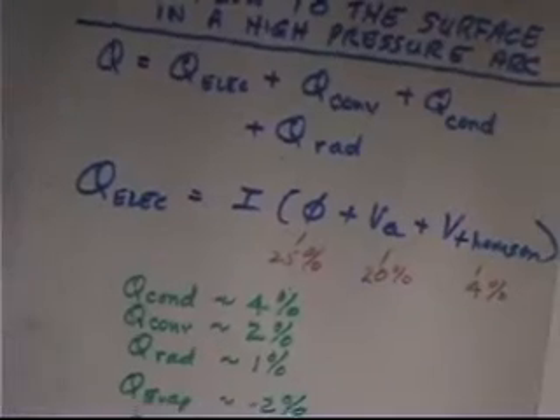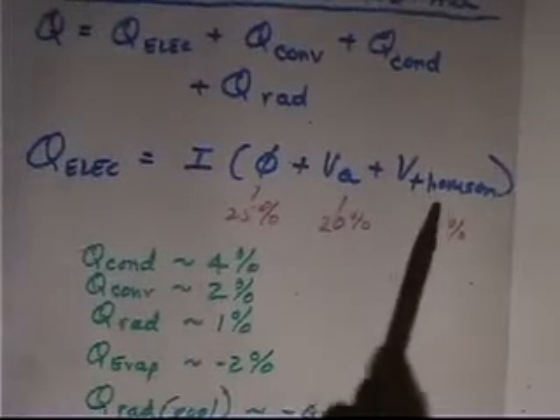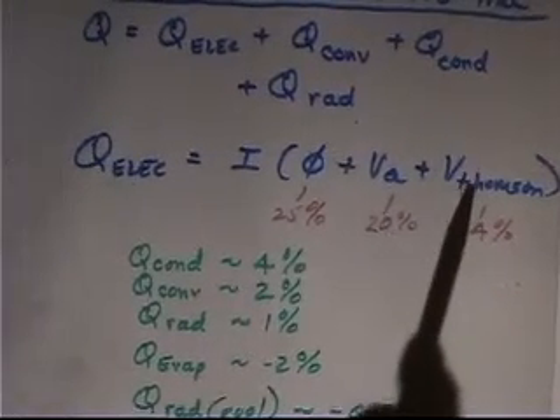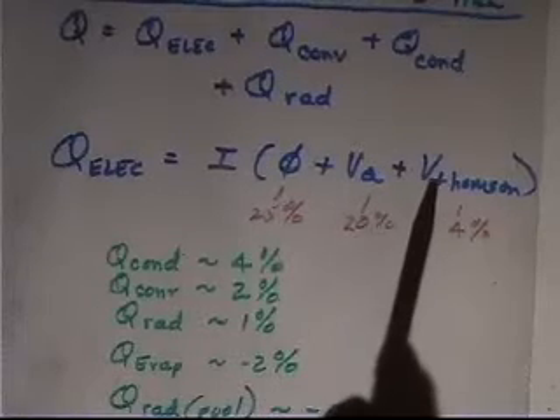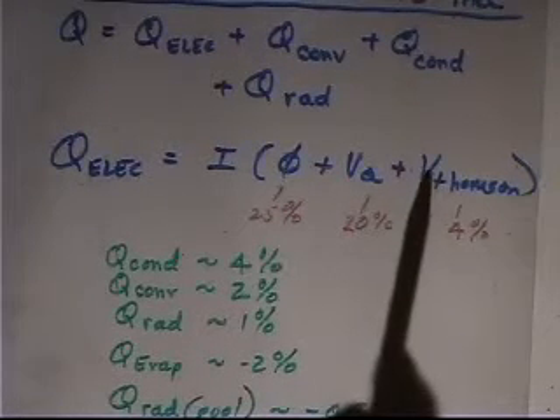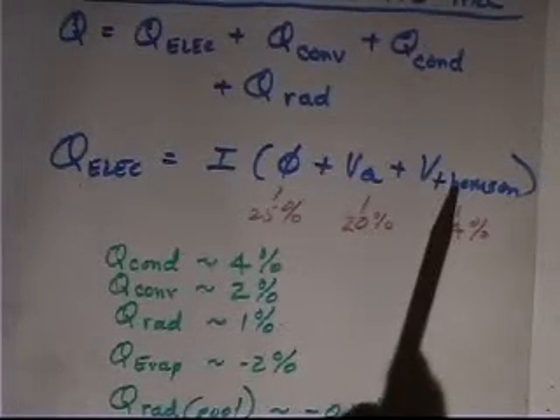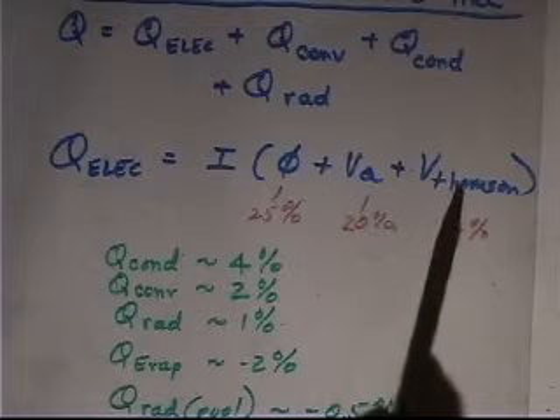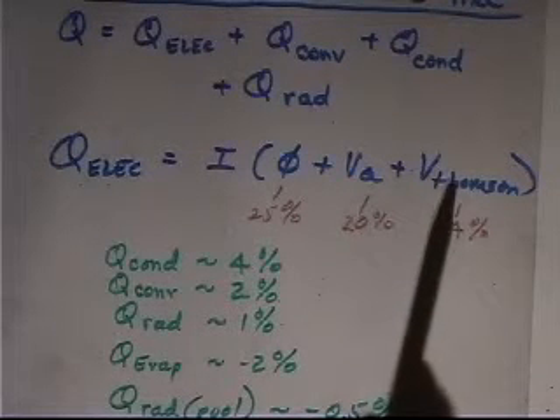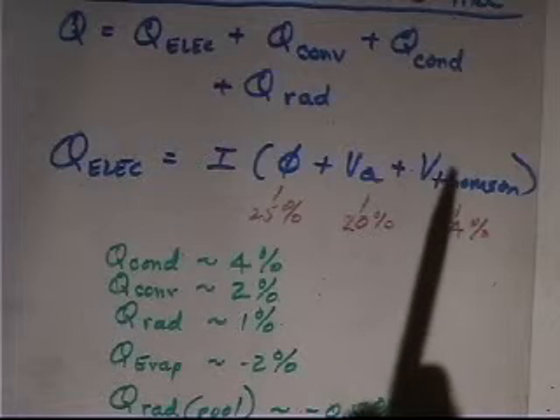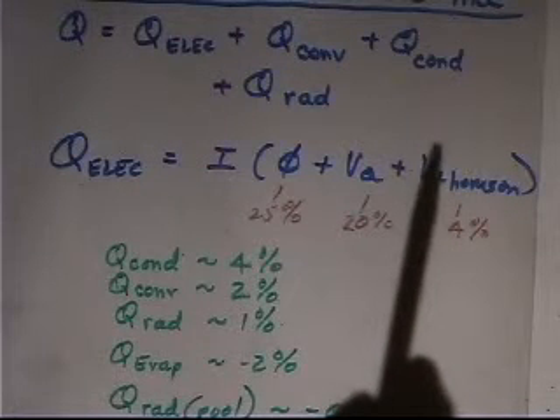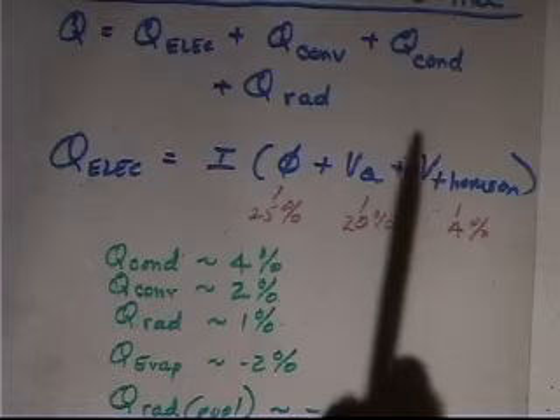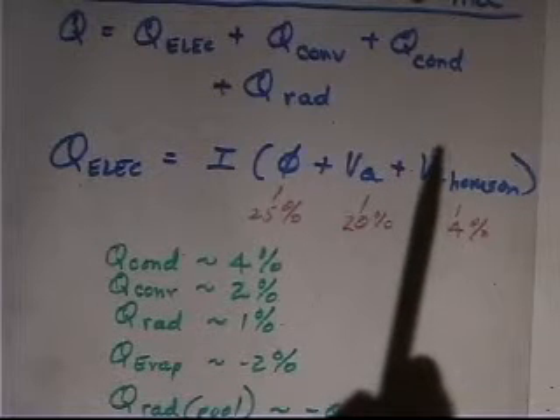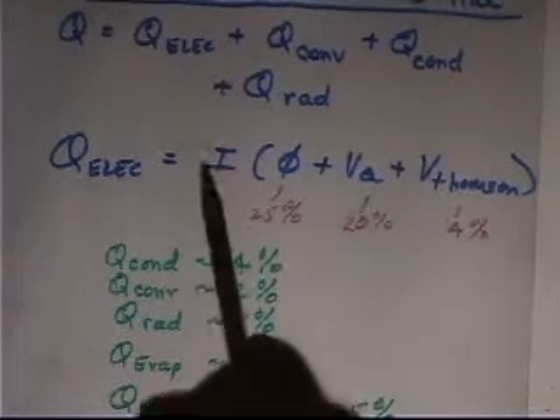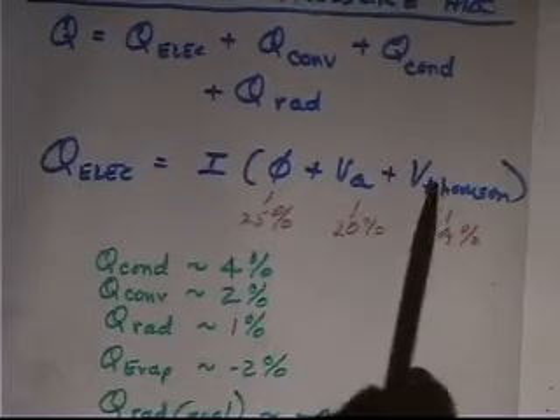Okay, so we know that the heat from the electrons, due to the fact that they're not at absolute zero temperature, but they're hot in the plasma, if an electron's in the middle of a plasma stationary, just because it's hot, it will have about 1 volt of thermal energy. Now, it's not going to give up all of that 1 volt. It's going to go into a weld pool that might be at 2,000 degrees rather than 10,000 degrees, so it may only give up 0.8 of its volt, of its Thomson energy, when it condenses into the lower temperature metal. But nonetheless, the Thomson energy is going to be something.